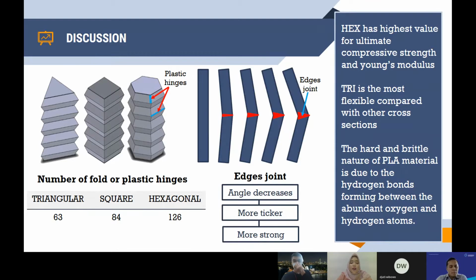The first reason is the number of folds or plastic hinges. The hexagonal specimen has 126 plastic hinges, while the triangular has only 63, which is half of the hexagonal. In the 3D printing process, there are several things that cannot be avoided. One is increasing the thickness at the meeting point of edges. As the angle decreases, the thickness of the meeting point increases, becoming thicker. This thicker structure will cause the structure to withstand more energy.